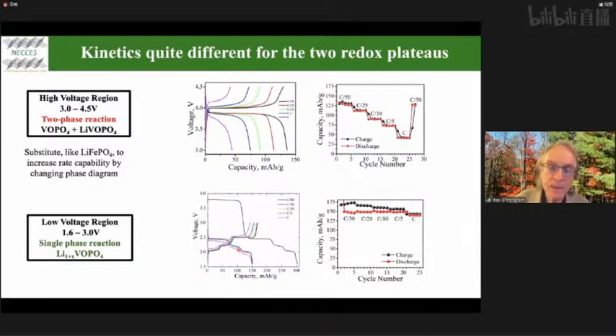There's a bit of a difference here due to the resistance of the electrolyte. So this is an exceptionally high rate, but there are challenges. Here is the discharge capacity in red. Very, very stable, independent almost of the rate.